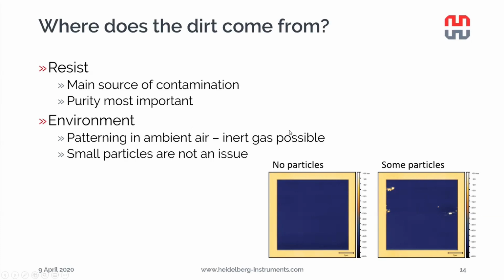We actually wouldn't even need a clean room or inert gas, as we can run the NanoFrazor quite nicely in an office building. Also, particles on the surface are not nice, but usually don't affect the patterning that much. Here we have an example where we've seen some particles on the surface, but as you can see, everything around the particle looks just fine. So the feedback had no trouble working around these particles and fixing these small changes.